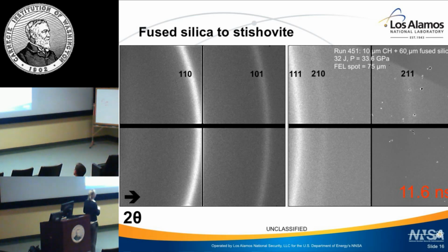Moreover, we can say the nature of the diffraction here is that we're not getting much preferred orientation. I admit the azimuthal coverage here, so this direction of the diffraction, we don't have a lot of coverage, but we don't see anything obvious initially. And the peaks are fairly broad, right? It's sort of diffuse, so you might assume small-ish grain size, right?